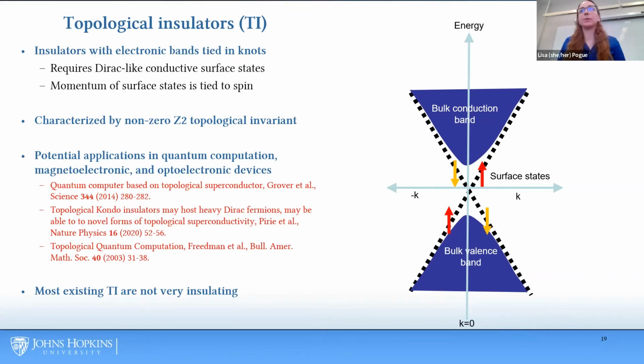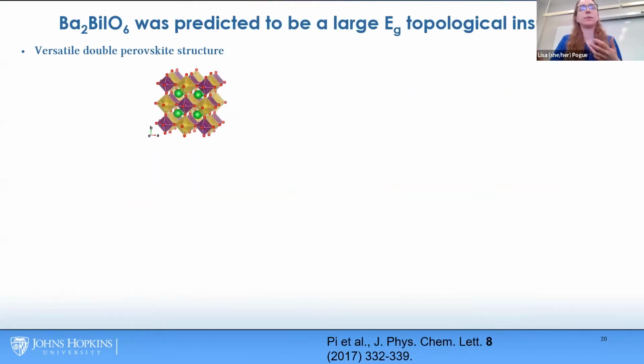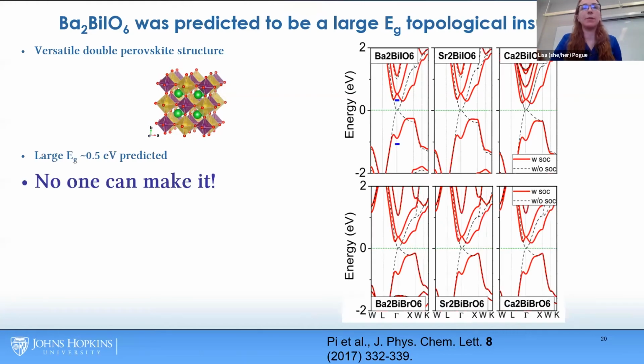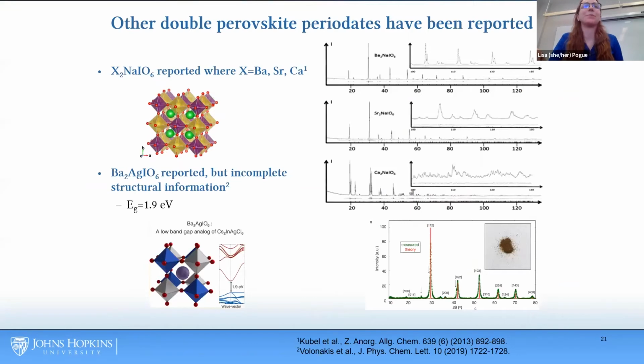Most topological insulators that have been reported are not very insulating, and it's tricky to get them to be insulating because of defects. And so I went to look to see if I could make or come up with a larger band gap topological insulator. Barium bismuth periodate had been predicted to be a large gap TI, but no one had made it. And this was a problem, as you can imagine.